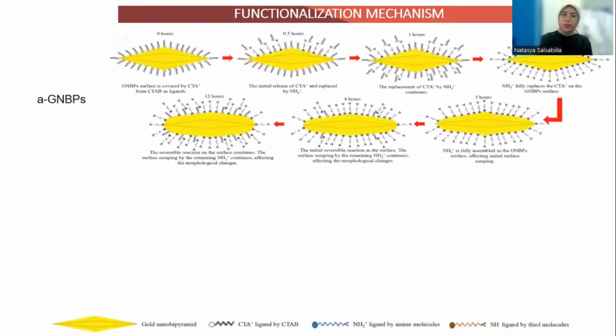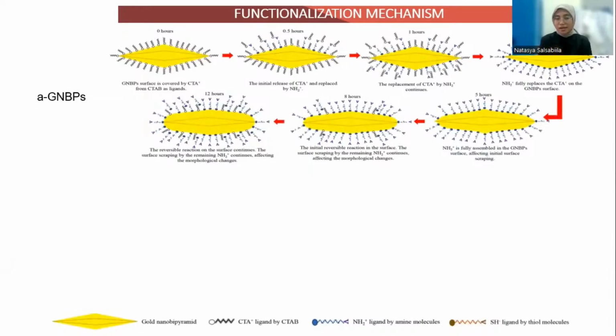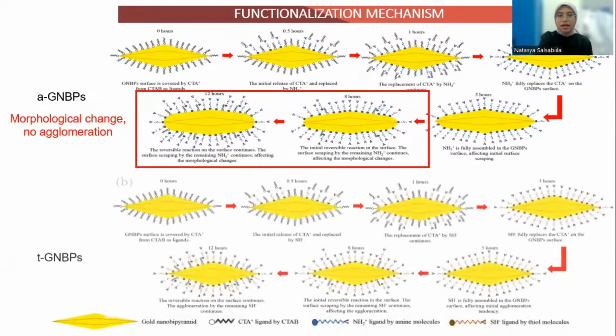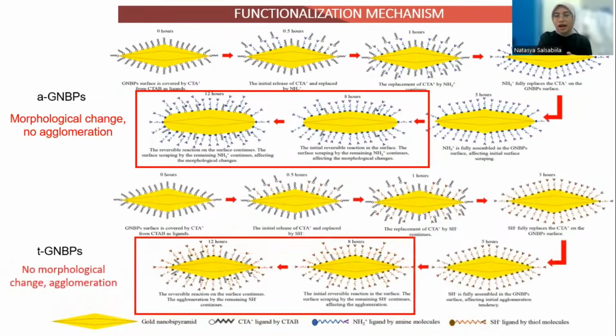Yeah, we already know how to synthesize and functionalize gold nanobipyramids or GNBPs, and we also know about the properties change after the functionalization process, and here is the proposed mechanism of functionalization itself. So amine groups can influence the morphological change, while thiol allows for nanoparticle agglomeration. So this corresponds with the general understanding of zeta potential value, where positive charge of amine influences agglomeration inhibition, and vice versa for negative charge of thiol.